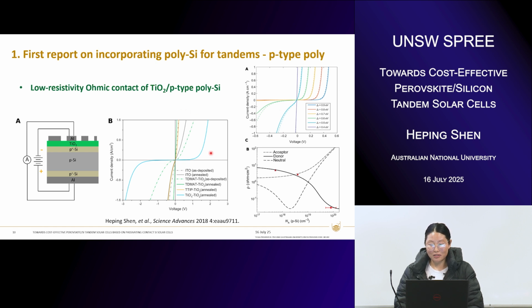As you can see from these contact testing IV curves here, like this bright blue color, they are rectifying. But for some certain smartly engineered titanium oxide material, we find that it can give us such a low resistivity ohmic contact between this titanium oxide and the P+, and it is such a contact that enables us to have a good performance for the tandem. It is such an interesting, innovative structure.